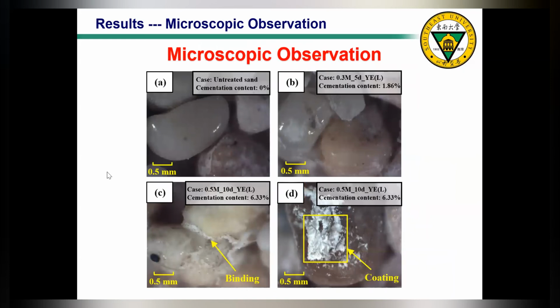Then we also performed microscopic observation using optical microscopes. In picture A, this is uncemented sand: loose sand without any cementation or bonding between particles. For figure B, this is a low cementation level case. We can see a little bit of interparticle bonding, but not that obvious. However, for the heavily cemented case, with 6.33% cementation, we can see quite obvious, wide interparticle bonding or cementation between the sand particles. In addition, we also see many calcareous sand particles coated by this kind of white cementation. So these 2 graphs prove that the biocementation was effectively generated.